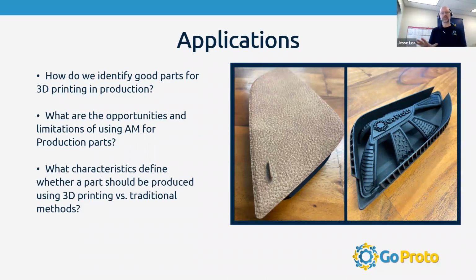Right now the technologies are pretty similar, but multi-jet fusion's basic architecture has a much longer road, a much bigger bunch of applications, because they can do different materials, not just polyamide based, which is really exciting. And with that basic technology of applying voxels, you can change all kinds of things. You can also potentially do metals, which they're looking at getting into, and elastomers. We are also getting better results in general right now with density. Parts are stronger. David mentioned isotropic properties earlier. Multi-jet fusion is more isotropic than really any of the other processes, including selective laser sintering, which means it's stronger in the Z than the other processes. So you get a more consistent part, 360 degrees.